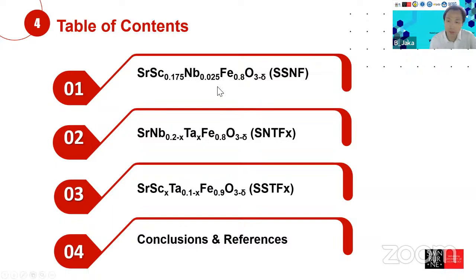Of course, in terms of the area-specific resistance and the performance in solid oxide fuel cells, if your perovskite contains cobalt, you expect that the electrochemical performance will be higher, but at the same time that will be traded off by your stability. So if you consider the lifetime performance, the one that contains cobalt will have its performance reduced more quickly compared to the one without cobalt.